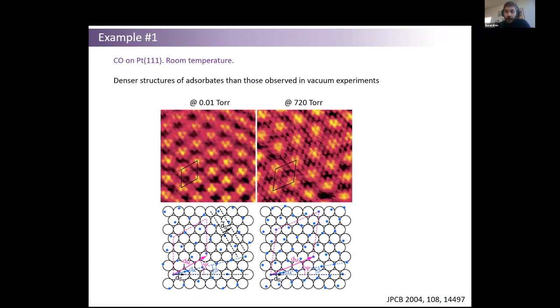So that was actually the most important outcome of this work, that one can reach a coverage of carbon monoxide that was not reached before in UHV studies. Now here, this carbon monoxide also forms ordered structures on the surfaces. And because the periodicity of carbon monoxide and the periodicity of the platinum 111 surface is different, it also forms a moire pattern. But the most important thing is not the moire pattern. The most important thing is that the adsorbate structure of carbon monoxide is quite dense. This was not observed before. And this was back in 2004.